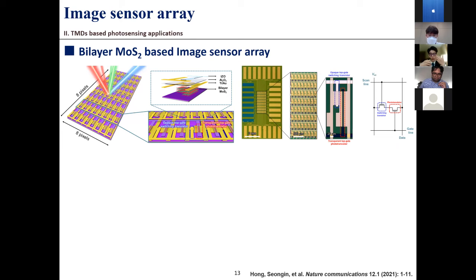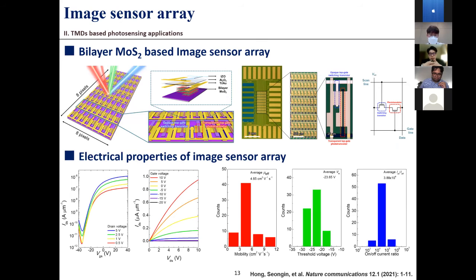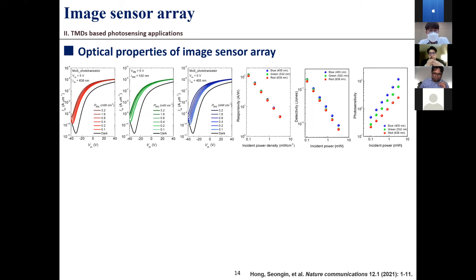This array is an 8x8 active matrix structure consisting of a switching transistor and a sensing transistor in 1 pixel. If you look at the electrical properties, the on and off current ratio shows very good performance, over 10 to the 5, and the average field effect mobility of the 64 switching transistors is about 4.85 centimeter square per volt second. The optical characteristics of the array show good performance under red, green, and blue illumination light, and the photoresponsivity, detectivity, and photosensitivity were extracted, which are important figures of merit for photosensing. And this responsivity is a world record.